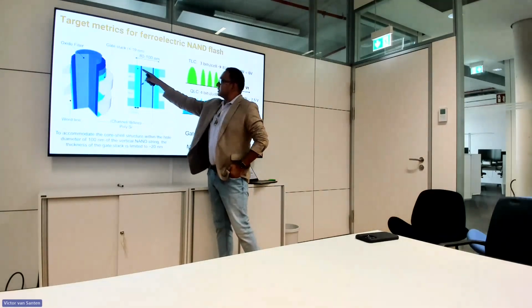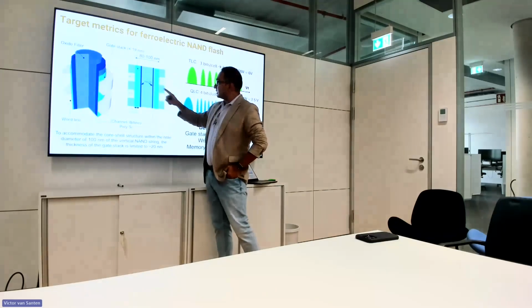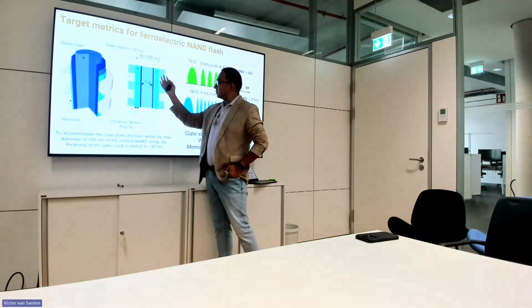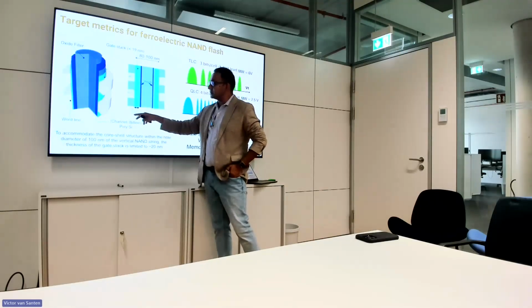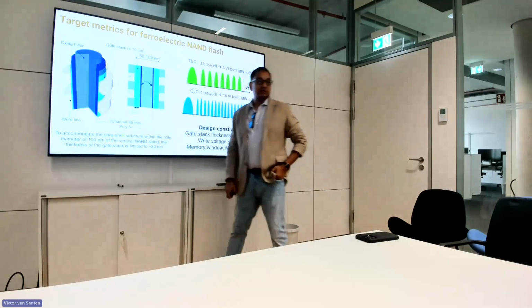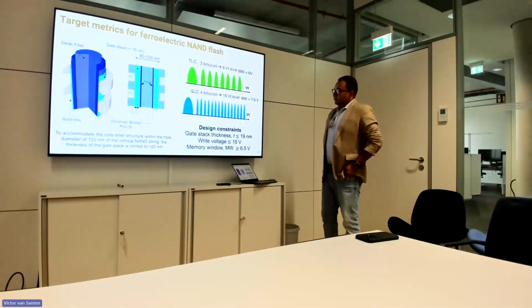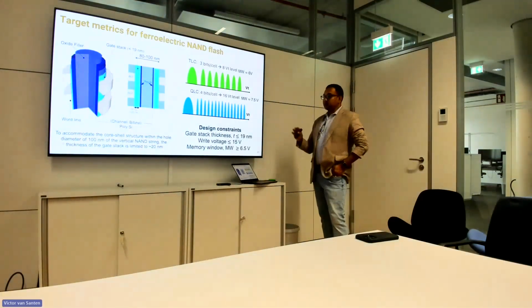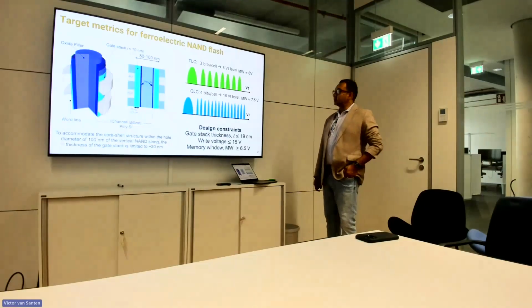Now the oxide filler is around 50 to 60 nanometers. The channel is around 10 nanometers. So that really leaves us a gate stack thickness of 20 nanometers. Okay. So the ferroelectric gate stack has to be around 20 nanometers. It cannot be more than that.